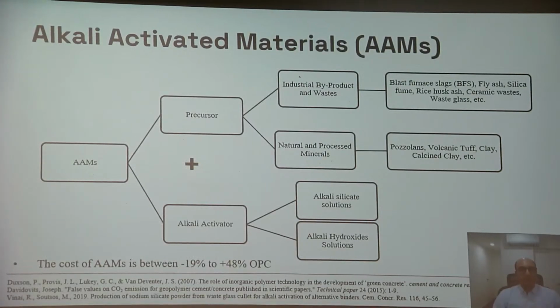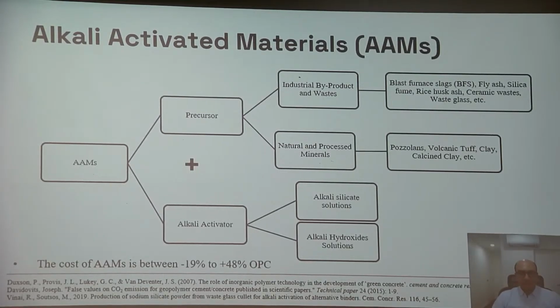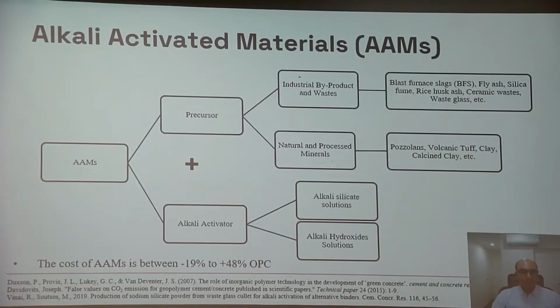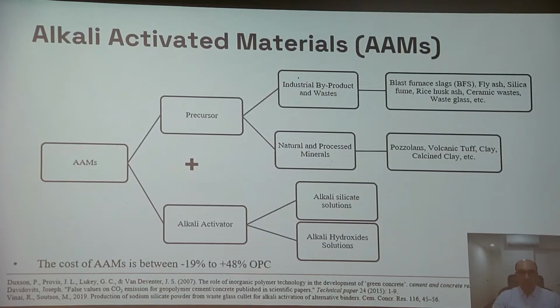AAMs are produced by combining precursors such as waste glass or industrial byproduct or waste with alkali activator like sodium silicate or sodium hydroxide or potassium hydroxide or potassium silicate. And there are different materials like natural and processed minerals that could also be used in alkali activated materials as precursors. The cost of the alkali activated materials could be different, depends on the type of the activator that is used and material that is processed. It could be 19% cheaper to 48% more expensive than the ordinary Portland cement.